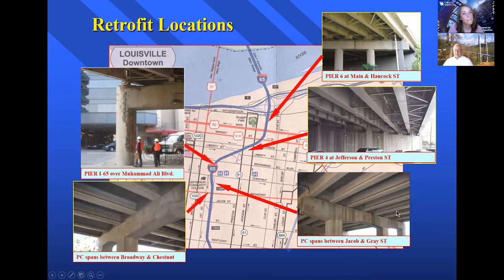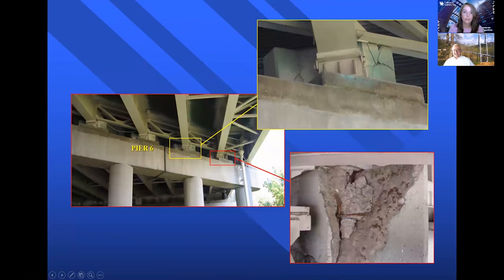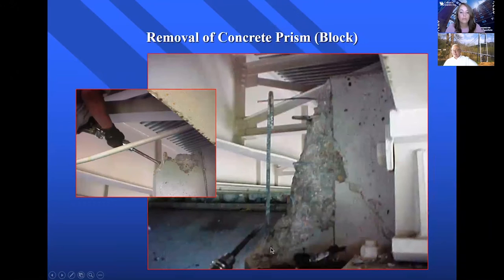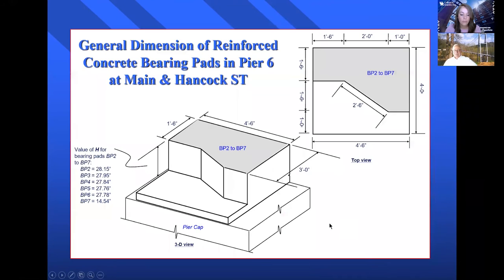Now, not only can we repair these beams and so on, but there are many facets of these fabrics that are really very good in repairs. This is the elevated portion of I-65 in Louisville as we approach the Ohio River. I'm going to highlight this section. The pedestals in here were really cracked, extensive cracking in them actually. And when you start removing the bad concrete, in some cases, we ended up removing almost 90% of the concrete in that pedestal. The original shape of the pedestal was something as such.